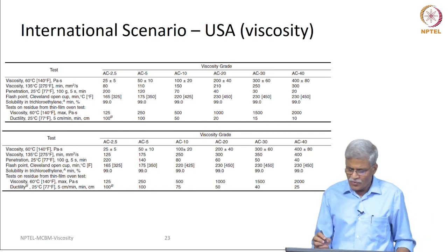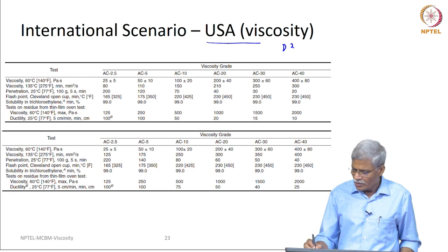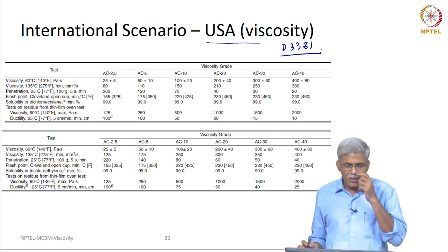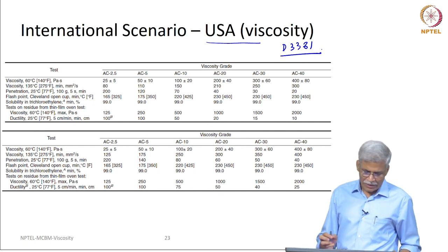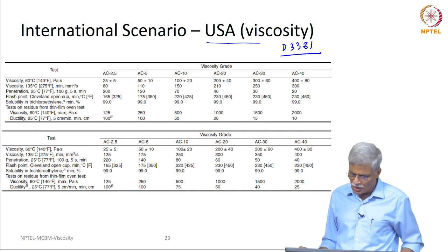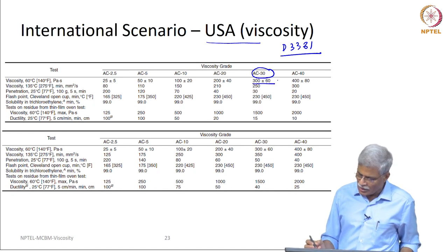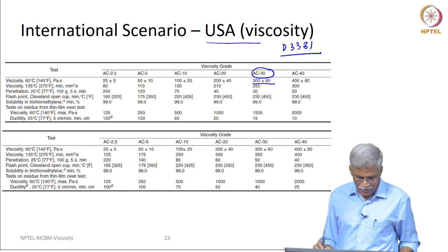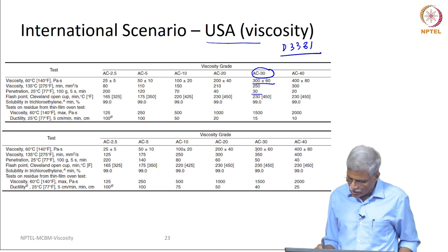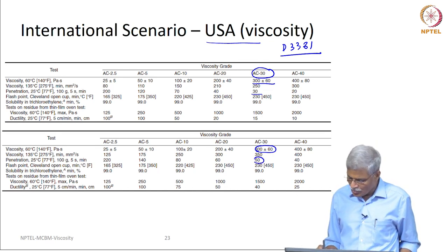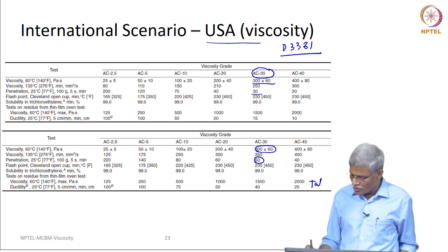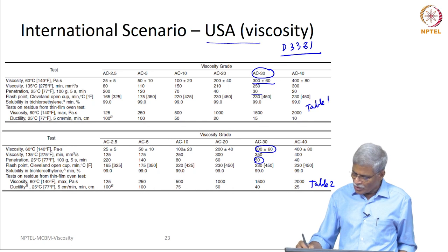This specification is based in USA: ASTM D3381. ASTM gives this in two tables — Table 1 and Table 2. Please take a moment and look at these two tables and then we will focus our attention on AC 30, with viscosity of 300 plus or minus 60 at 60 degree centigrade and penetration at 25 degree centigrade of 30 in Table 1, and penetration of 50 in Table 2.